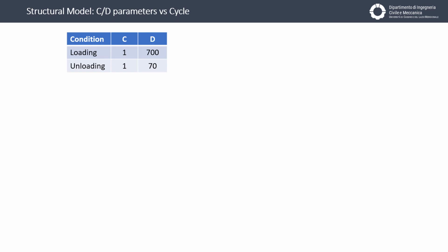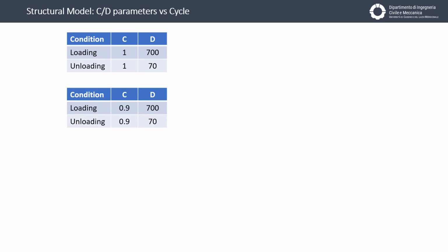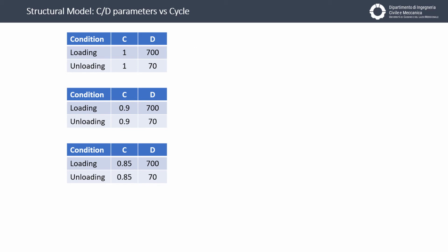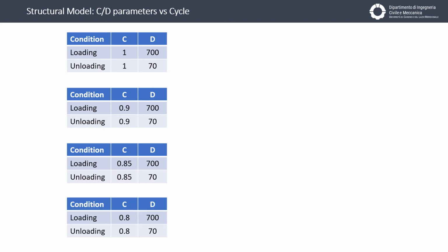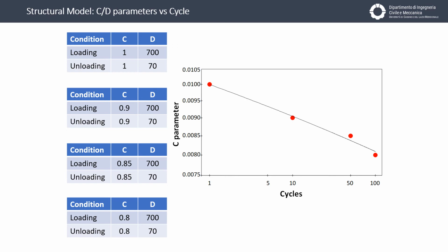Calculating the parameters not only for the first cycle but for the 10th cycle, you can see that the parameter C changes from 1 to 0.9 and the parameter D are always the same in the loading and unloading conditions. Next, at the 50th cycle, the parameter C decreases again, and after 100 cycles decreases too. Plotting the parameter C in terms of the cycles, you can see a behavior like this. It means that the parameter C takes into account a sort of fatigue effect in the shape memory alloys.